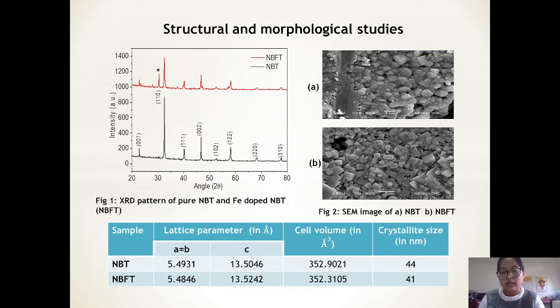The crystallite size of the samples was also calculated using the Scherrer formula, and it was found to be around 40 to 45 nanometer. Figure 2 shows the SEM image of the sodium bismuth titanate and the doped sample, and we can see that the particles are uniformly distributed with an average particle size of less than 1 micrometer.